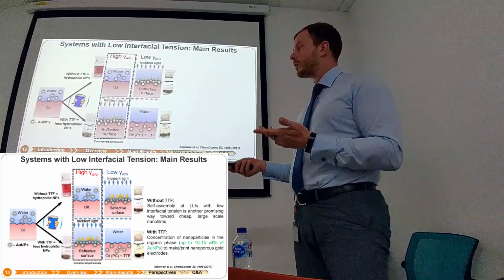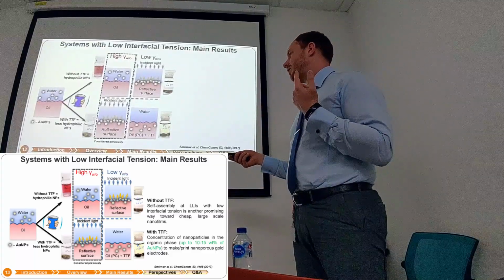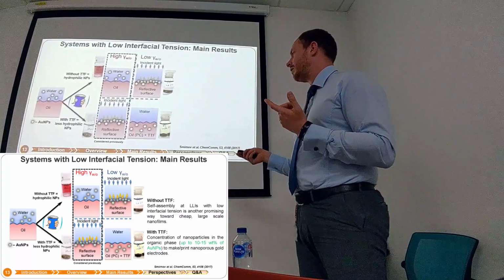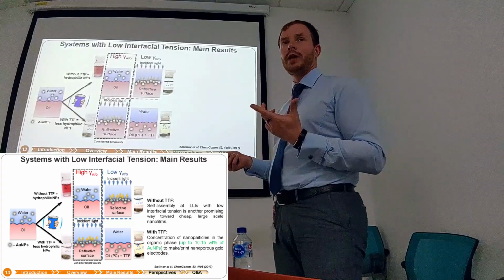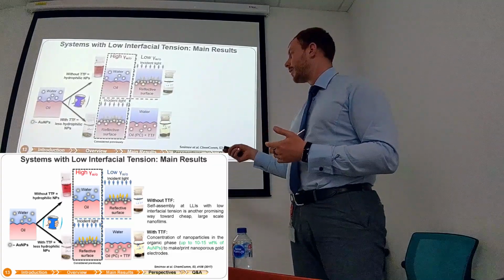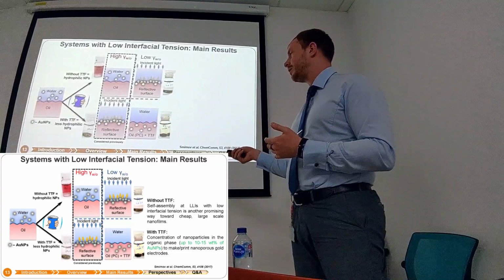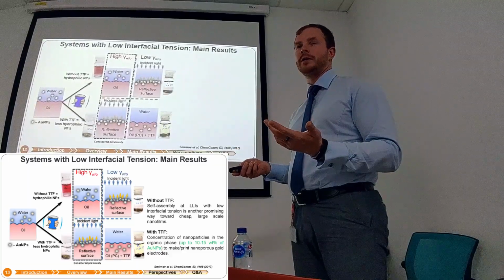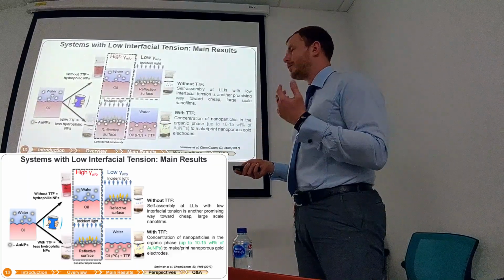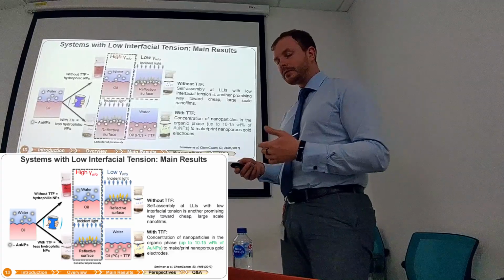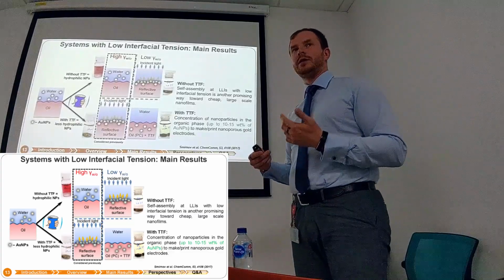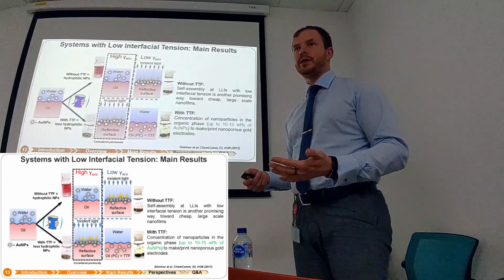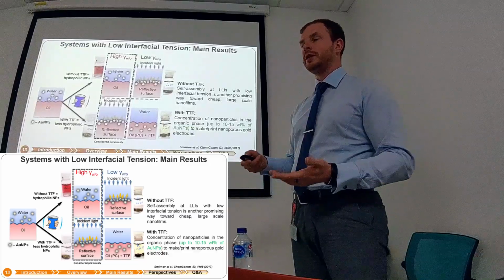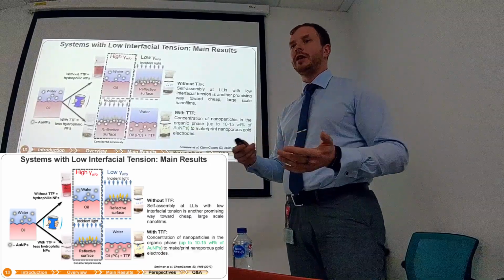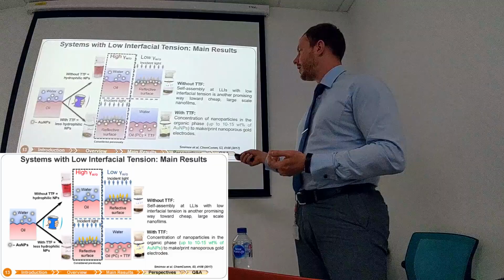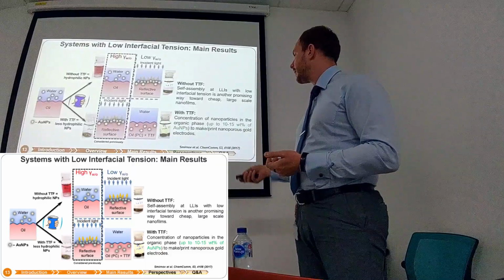It means that in principle we can easily industrialize this process and make square meters of such film. But more important, if we take TTF and, for example, propylene carbonate, and mix them, nanoparticles are transferred from water to the propylene carbonate phase. This is a bit unusual because normally nanoparticles don't like to be in an organic phase, because of screening charge, energy balance, and so on. But here we managed to transfer them.